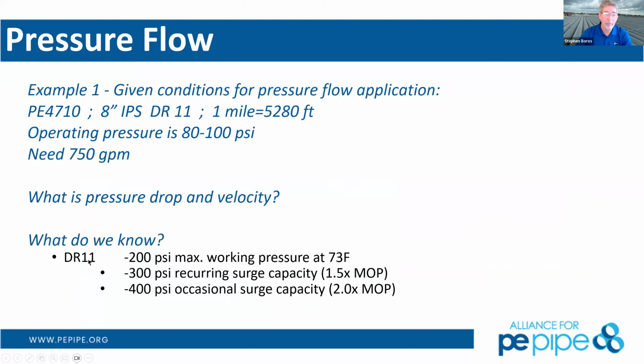So we know right off the bat, without even going to the software, that DR-11 has a max pressure rating of 200 PSI at 73 degrees. It's also going to have 1.5 times that in your recurring surge capacity. That's up to 300 PSI. So 200 plus another 100 gives you 300 PSI surge capacity on an everyday basis, 10 million cycles, 55 cycles a day for 100 years. And occasional surges, which is going to be a few million cycles over 100 years, at 400 PSI, double the pressure class or pressure rating. So we know that just off the bat.